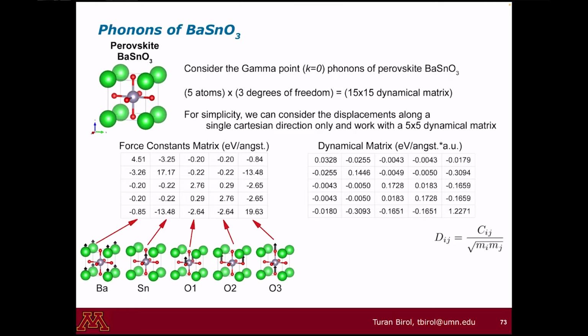Depends. I would say so. This material is electronically almost like a vegetable, right? It's a wide bandgap insulator. There isn't very strong spin-orbit coupling and so on. So here I would be confident that my error bar is pretty small, like perhaps 0.1 eV per Angstrom, perhaps even smaller. But this should be Angstrom squared, right? Because electron volt per Angstrom would be force, not force constant.